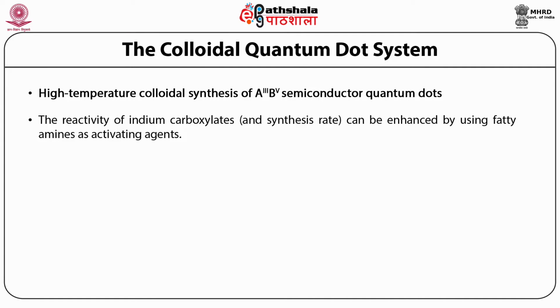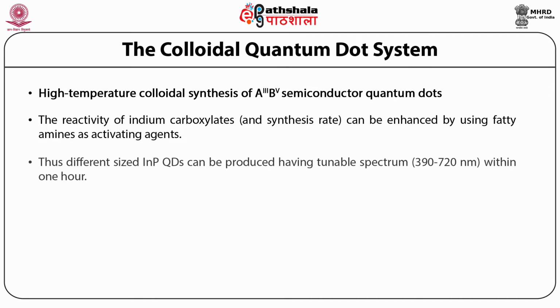The reactivity of indium carboxylates and synthesis rates can be enhanced by using fatty amines as activating agents. Different sized indium phosphide quantum dots can be produced, having a tunable spectrum from 390 to 720 nanometers within 1 hour. The phosphorus source is also important for synthesizing indium phosphide quantum dots.